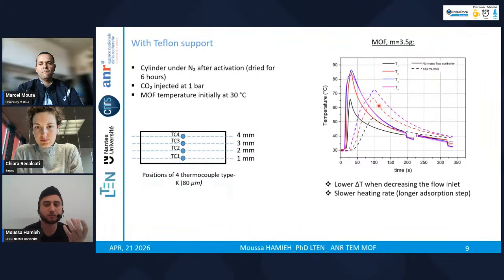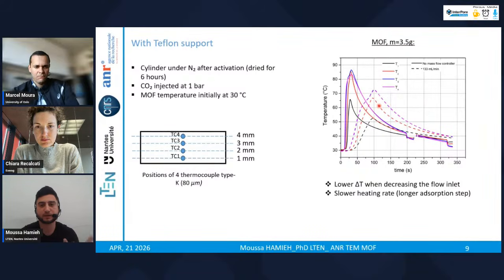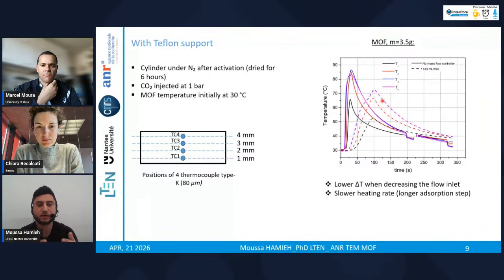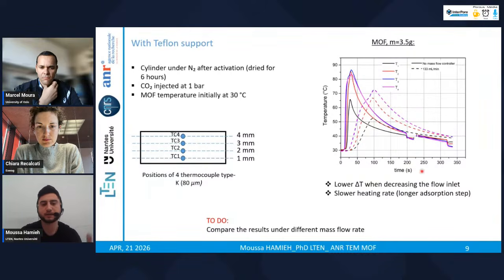Here we cannot compare the real behavior of absorption because we don't have the data of the quantity absorbed. So the CO2 analyzer is needed to see the difference of behavior between the two cases. But this also gives us an idea that the mass flow rate is a parameter involved in the behavior of the materials, since it depends on whether the CO2 fills the entire volume of the cylinder before the time required for the MOF to be heated, and so the temperature increases in the MOF. So what we will do is compare at different mass flow rates, for example, from 100 to 500. We will compare the results, and also not only CO2, but a mixture of CO2 and nitrogen.